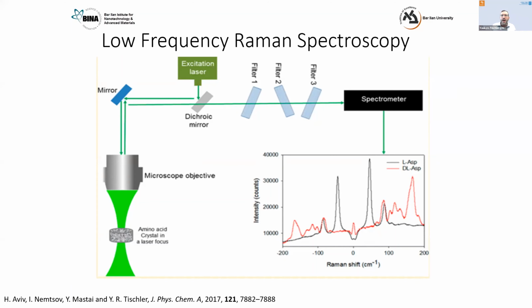make a small change in the nanostructure, and those small changes in the nanostructure become apparent in the low frequency regime. So I would argue, and this is the direction we've been following for some time now, that the low frequency Raman scattering range is really, really well tuned for studying very small differences in nanostructure.